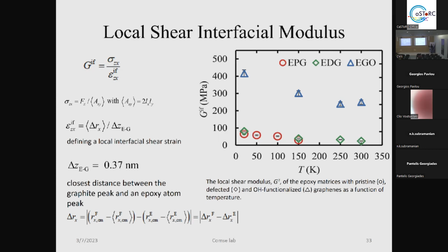Okay, if you change F now, if for example you use 1.1 F, you increase by 10%. But that was the way that we calculate it. We changed F every time. So this is from the slope between sigma and epsilon, not the ratio between sigma and epsilon. Do you use a constant force? No, we change it every time.